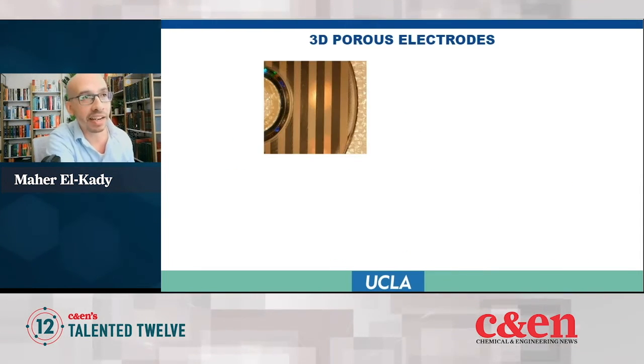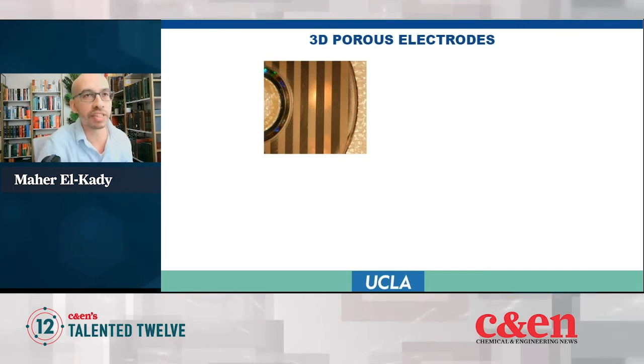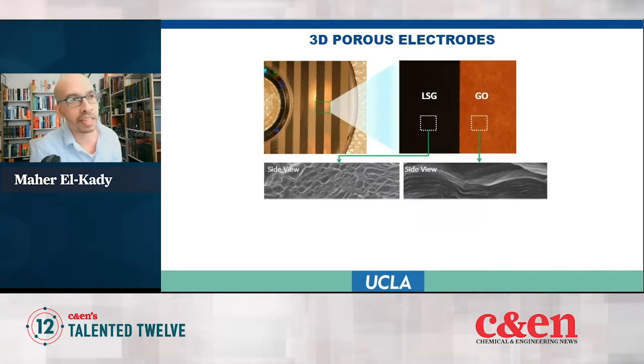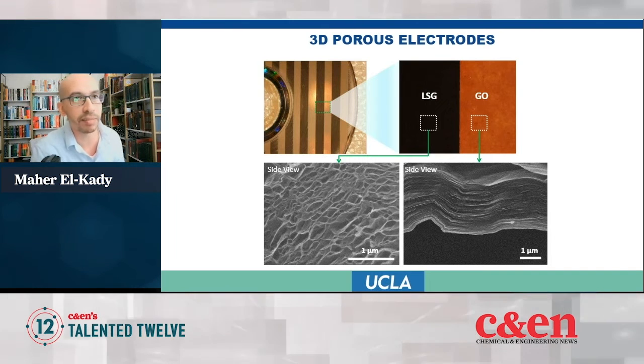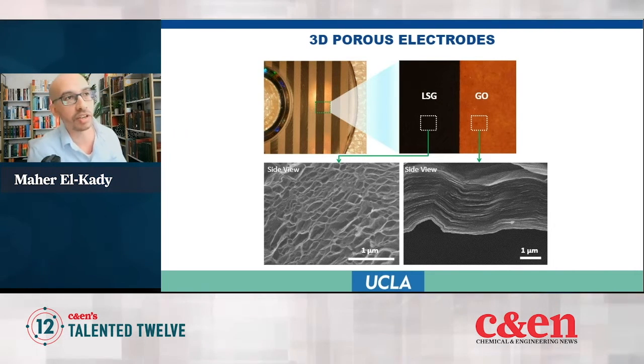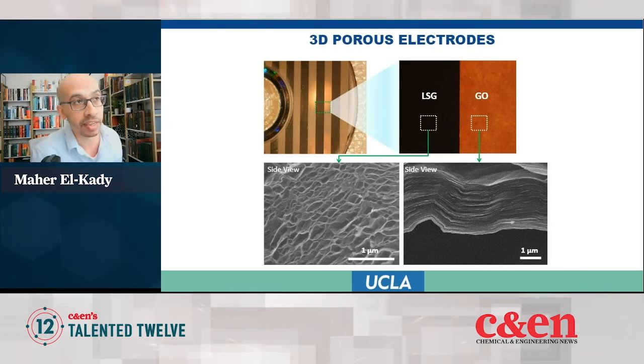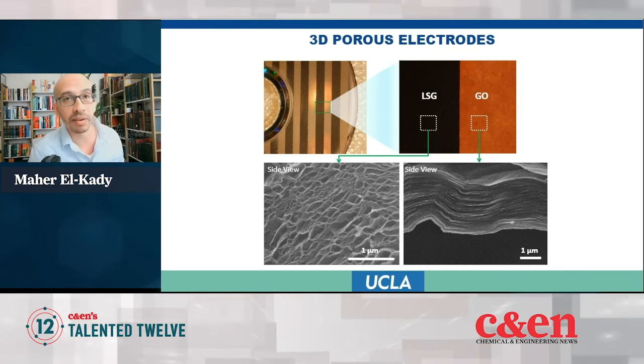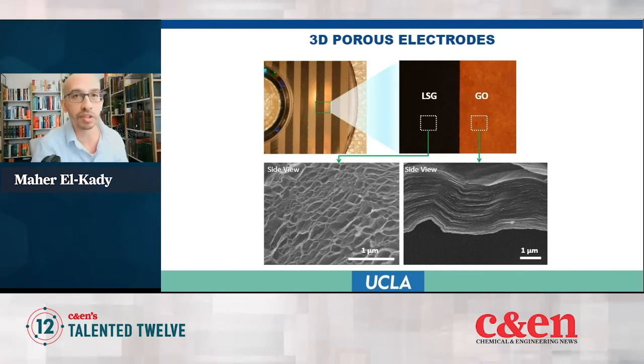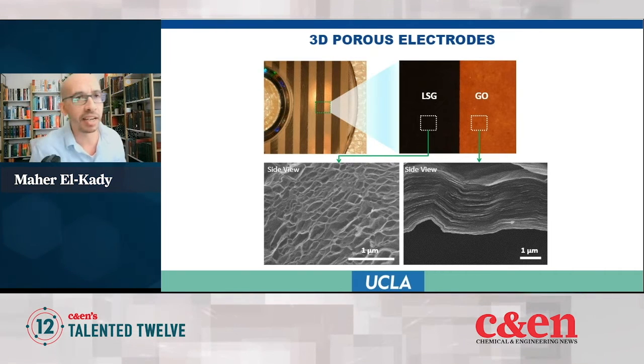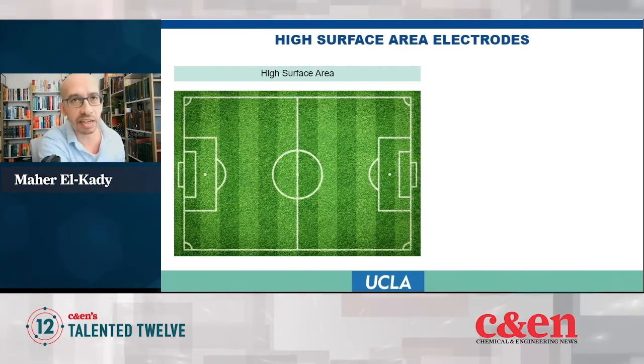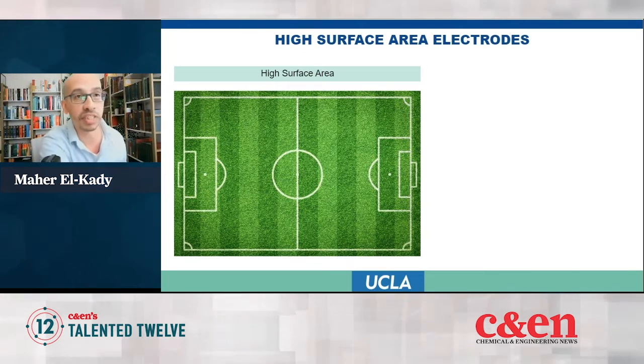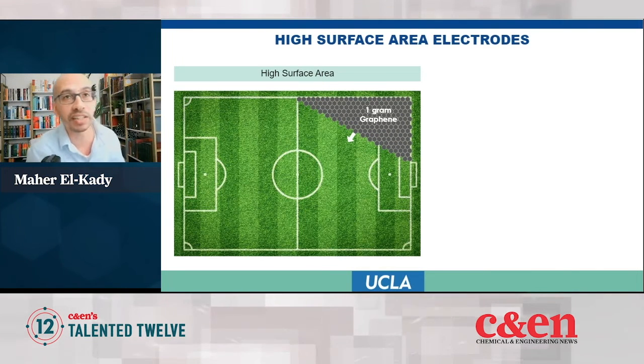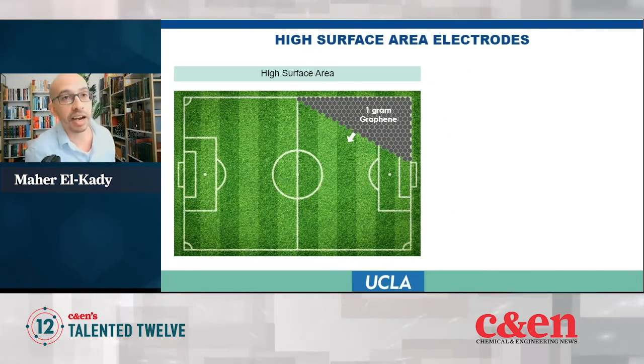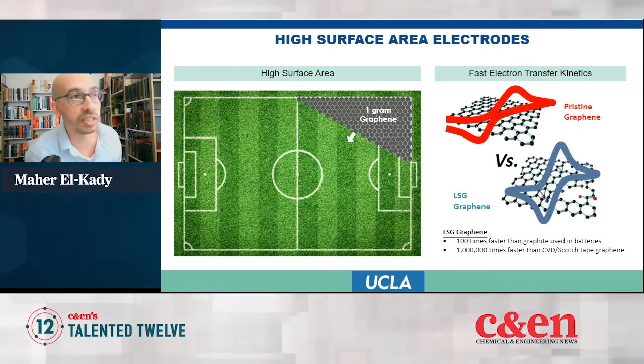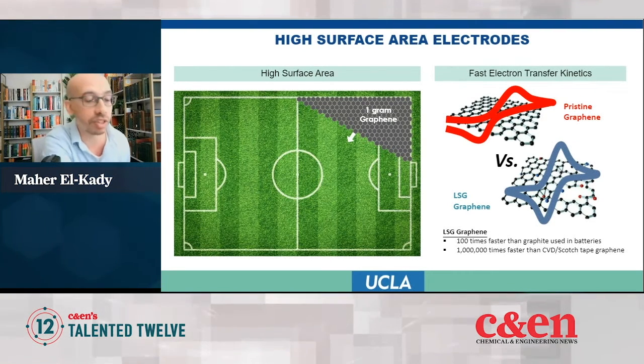When we analyzed the microstructure of these electrodes, we found something interesting. Graphite oxide has a similar structure to graphite, not surprisingly, but the graphene had a sponge-like structure with a lot of porosity. When we measured the surface area, we found that it's got more than 2,000 square meters per gram. What does that mean? Basically, 1 gram of graphene could stretch to cover an entire football field. It's amazing. And this is also combined with very fast electron transfer rates. It can transfer electrons on its surface about 100 times faster than graphite used in today's batteries.